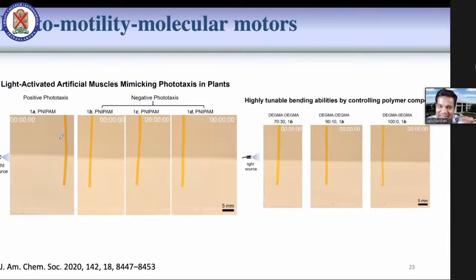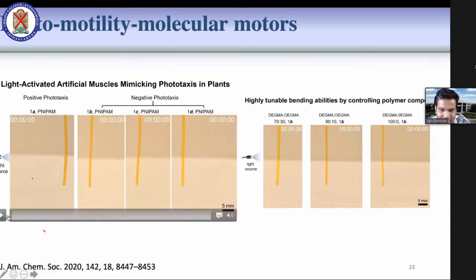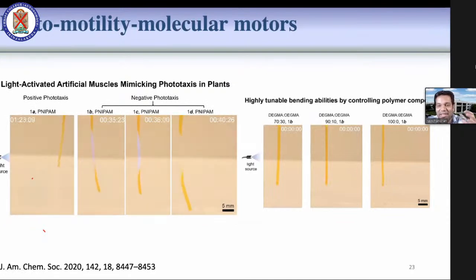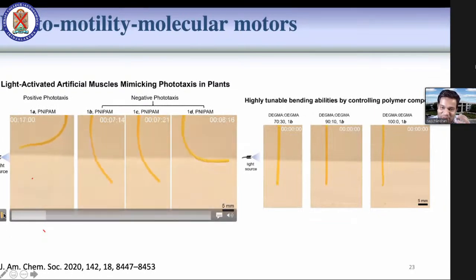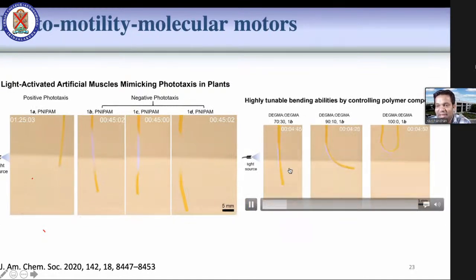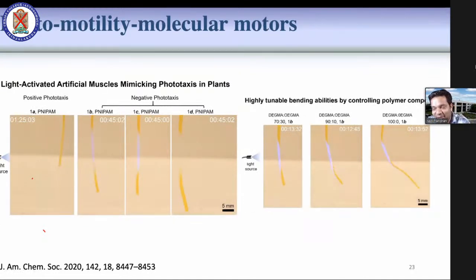This is the real cross-linked gel material with different materials. When we expose it to light, it starts swelling and shrinking, which induces motion of the material. When we hit it with light, it goes to the shrinking state, which folds, and bends at 45 degrees. And when it is at room temperature in a dark room, it comes back. It's the same with a different polymer. You can create any different cross-linked network.